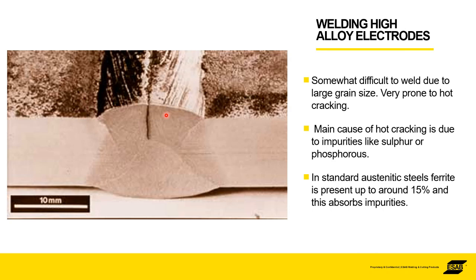This type of hot cracking is easy to reproduce in something like a super austenitic, where there's no ferrite in there. As I mentioned, the ferritic structure has gaps in it that can compensate for any kind of impurities. So if you have a super austenitic that has zero ferrite, then it's not very forgiving of impurities that are in there.